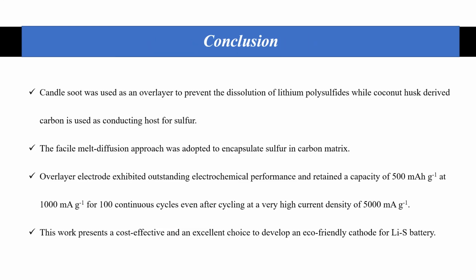Now, concluding this work, candle soot carbon was used as an overlayer to prevent the dissolution of lithium polysulfide, while coconut husk carbon was used as a conducting host. To prepare the composite with sulfur, a melt diffusion strategy was employed. When tested as cathode for lithium sulfur batteries, it delivered a capacity of 500 mAh per gram after 100 cycles at 1000 mA per gram. This work presents a cost-effective and excellent choice to develop an eco-friendly cathode material for lithium sulfur battery.